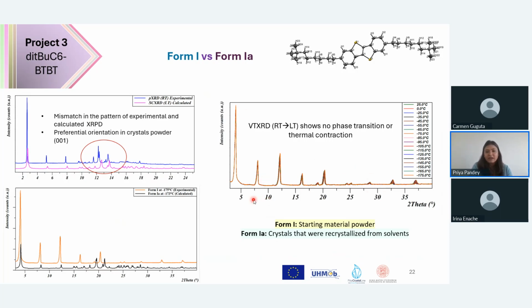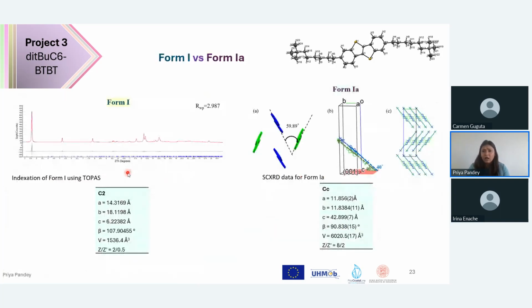Doing a variable temperature XRD actually confirmed that there is no phase change or thermal contraction, which means that the crystals crystallized from form 1 were actually a bit different from the starting material form, although very similar because most of the peaks were still matching. For that, since we already had the crystals of form 1A, I collected them using single crystal XRD and found the unit cell, while form 1 was a powder, which I indexed using TOPAS. And I found that actually these two are different forms, which was really hard to notice at first, but thanks to the synchrotron data, I could notice the difference in the polymorphs.